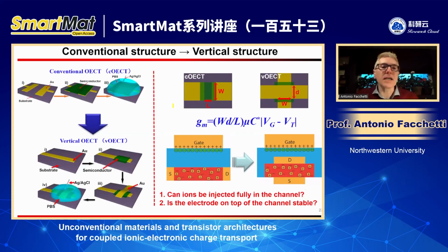And the way we did it is to go from a conventional OECT architecture, which is planar. Here you use photolithography, and this distance is a micron, to a vertical architecture, where basically you deposit the first gold line, the semiconductor. It doesn't have to be patterned, as a matter of fact. Then you deposit, cross bar, a second gold line, and this distance is the thickness of the semiconductor. Basically, this distance here is the distance between the electrodes in this vertical architecture.